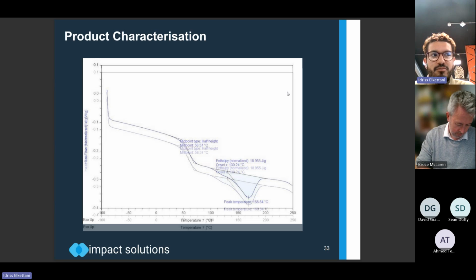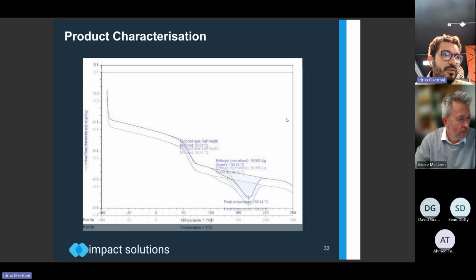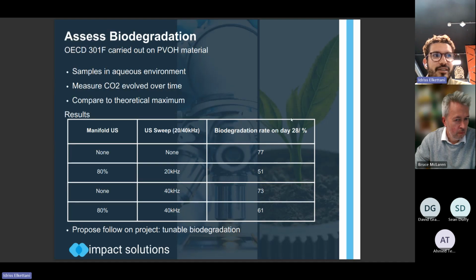We found that we managed to record a reduction in glass transition temperature of 5 degrees, which is significant but not meaningful for us. For the other polymers, so for the polypropylene, it had no effect. For the Ecovio, it had minimal effect. There was a 1-2 degree drop, but the most apparent drop in Tg was in the PVOH. So we thought it's a good opportunity to check out how the PVOH exposed to different ultrasonic parameters and what effect that has on the